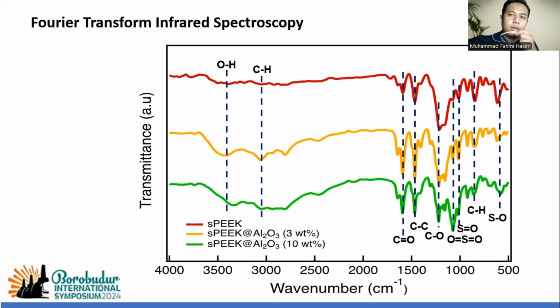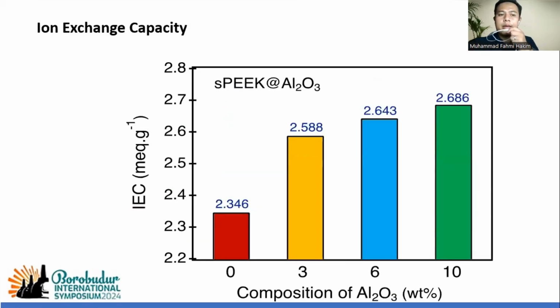Okay. And then about ion exchange capacity. A high ion exchange capacity indicates a high proton conductivity. You can see in the graphic that with the adding of aluminum oxide on the sPEEK membranes, the ion exchange capacity is increasing from 2.346 to 2.686 milliequivalent per gram.